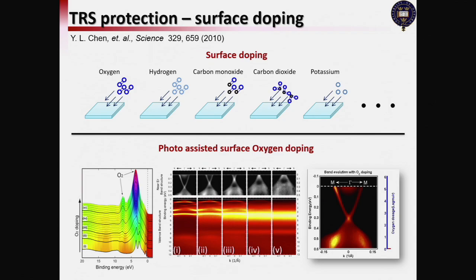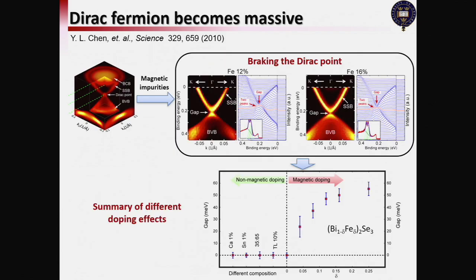And here is the cartoon. You can see that the chem potential keeps getting lower with more and more p doping, but the surface state dispersion persists. So if we put some potassium on the top, the chem potential will rise again, and then we'll see the surface state band. And you cannot do this to the bulk band. It's not reversible. So that means the surface state is stronger, more robust than the bulk band.